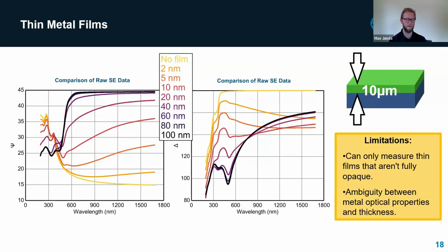The other thing is we have to know or make logical assumptions about what the properties of the metal actually are, because if we need to be fitting both the optical properties, N and K, for the metal and the thickness, we can get strong coupling between those where we have an ambiguity and we can't say for sure if we got the right optical properties or the right thickness together. So that's another limitation.